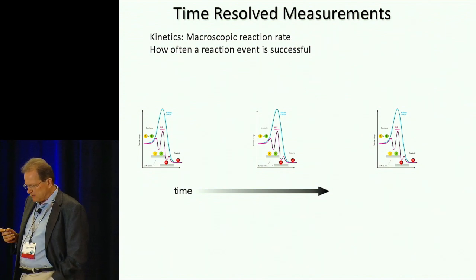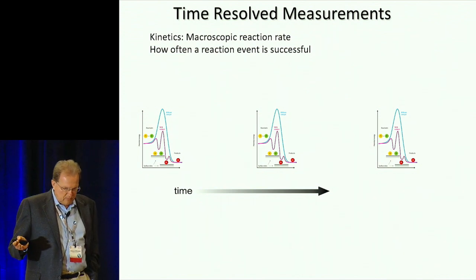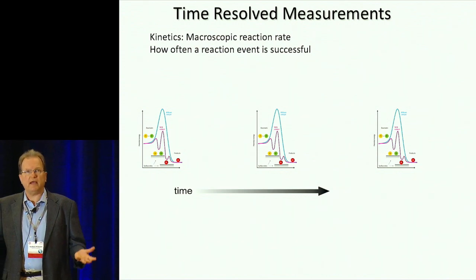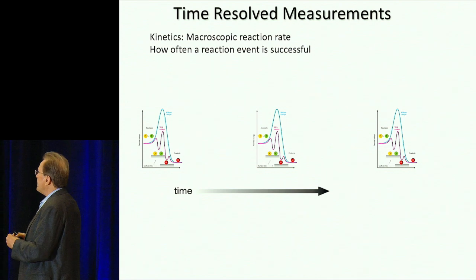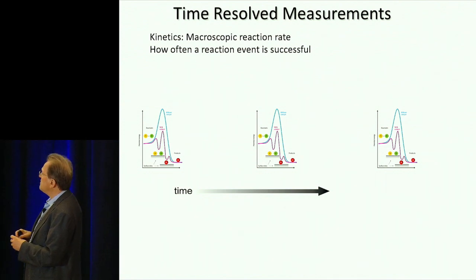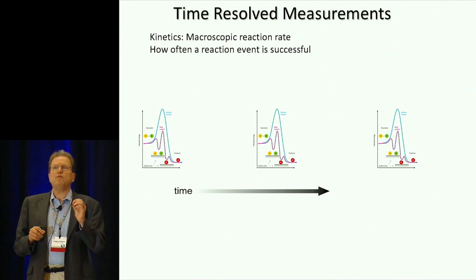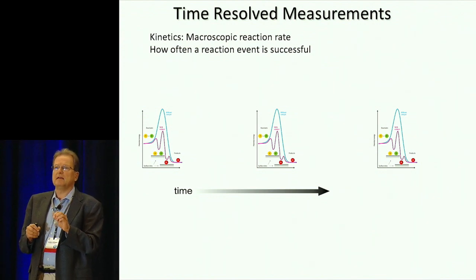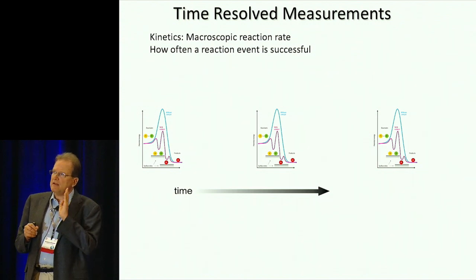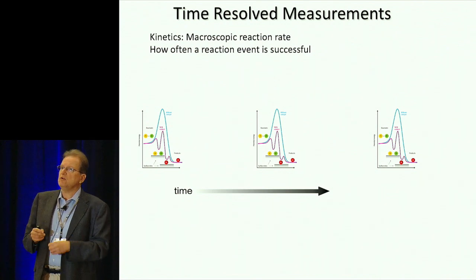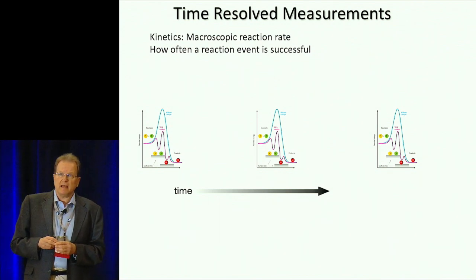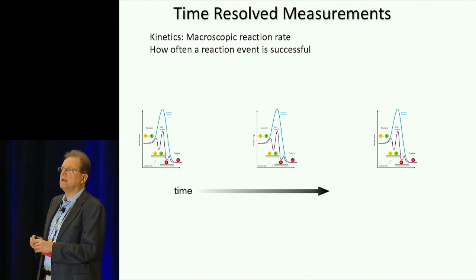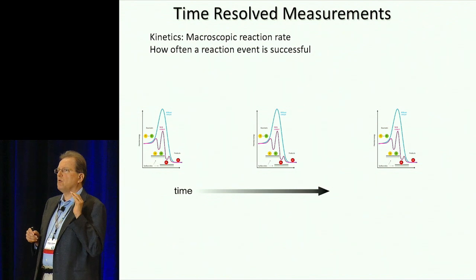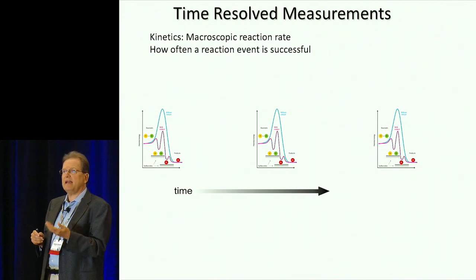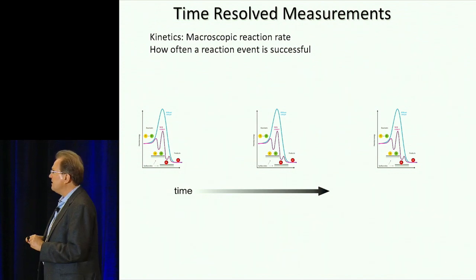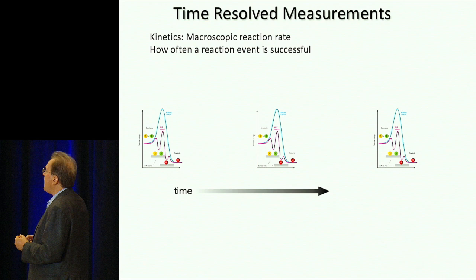We want to do time-resolved measurements to see that. And typically people do that all the time when they do chemistry. We measure reaction rates. I put this up a little bit like this: when you do a kinetic measurement and measure reaction rate, you are often measuring how often a reaction event is attempted and if it is successful or not. You're never really measuring as the reaction is happening. You're only measuring how often you have an attempt to make a reaction and if it is successful or not. And that might be just a few, what is called turnover frequency, a few turnovers per second or even per minute in many cases per active site. So you can't see really what's happening as the reaction is occurring.